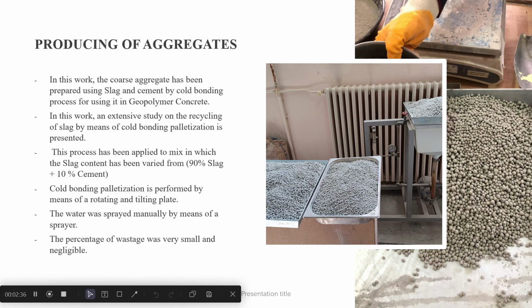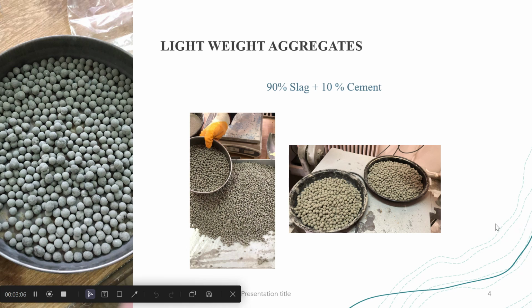This process has been applied to mixes in which the slag content has been varied, from 90% slag plus 10% cement. Cold bonding pelletization is performed by means of the rotating and tilting plate. The water was sprayed manually by means of the sprayer, and the percentage of the wastage was very small. As you can see, the lightweight aggregate of slag and cement.